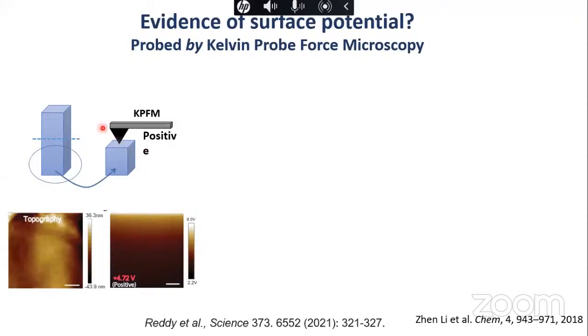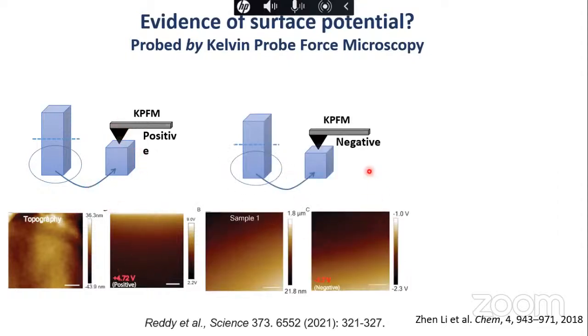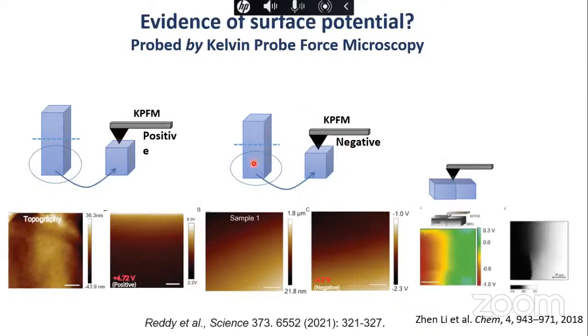Here you can actually map the surface charges. We took a crystal, mounted it, broke this part to create a fresh surface, and did the measurements. We found that there is actually a good amount of charge on the surface. Sometimes we found positive charge, and sometimes negative charge, because we didn't know the orientation, since these are non-centrosymmetric crystals. The orientation in the crystal is unique, and depending on whether you have it like this or the other way, you could have either positive or negative charge on the surface. So this tells us that there is a charge.